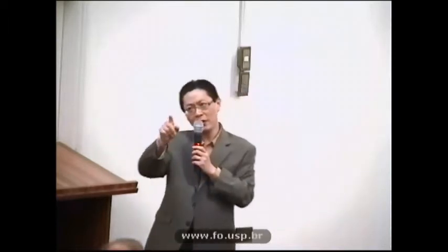Can you have a problem of misfit because you are infiltrating the glass in the inner side of the crown? That's his question. Very good question. You will have a residual glass layer about 20 to 50 micron thick. So there are two options. One, you can dial in the leeway when you do the CAD-CAM. Or two, you can etch it. After you infiltrate it, you use HF to remove the majority of the glass. That gives you a rough three-dimensional surface for cementation.